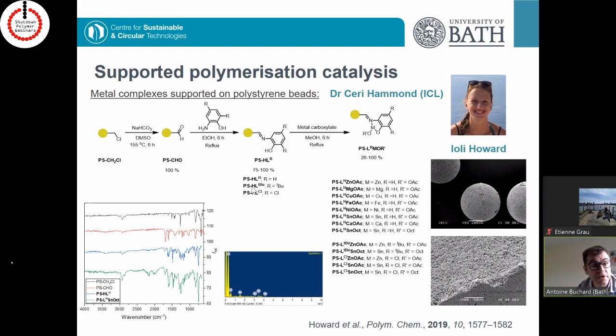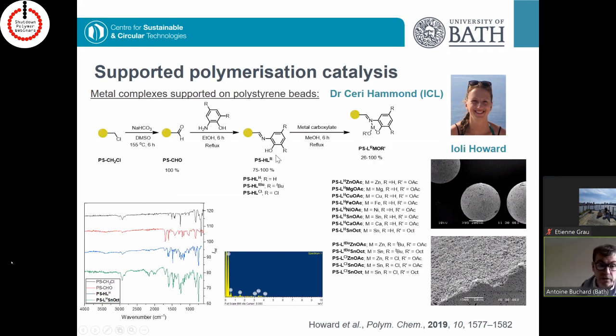So what Yoli did is she purchased some of this Merrifield resin, which is polystyrene functionalized by this CH2Cl chloride group. And using a bit of chemistry, what we've done is basically transform it into an aldehyde and then put this type of motif here, this NO ligand here. She's done a variety of variants of the ligand. So she's put some hydrogen here, some tert-butyl here, even some chloride. And then when we had this type of ligand framework grafted on the polystyrene beads, what we've been able to do is to complex a lot of metal carboxylate precursors using a simple procedure of reflux in methanol.